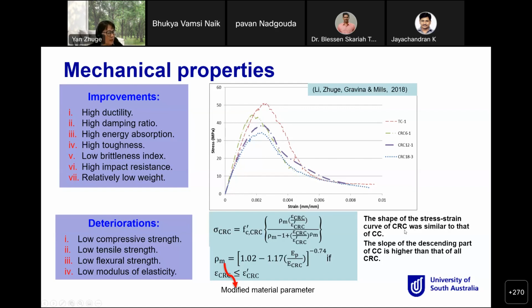The shape of the stress-strain curve for crumb rubber concrete is similar to normal concrete, and the slope of the descending part for normal concrete is steeper than that for crumb rubber concrete. You can see this here. The red color is normal concrete, and all the other colors are crumb rubber concrete. That is the comparison, and that is the stress-strain curve we developed.